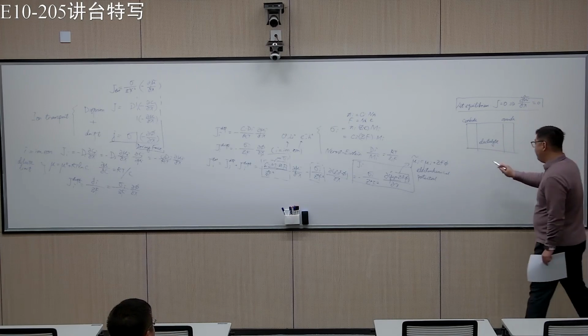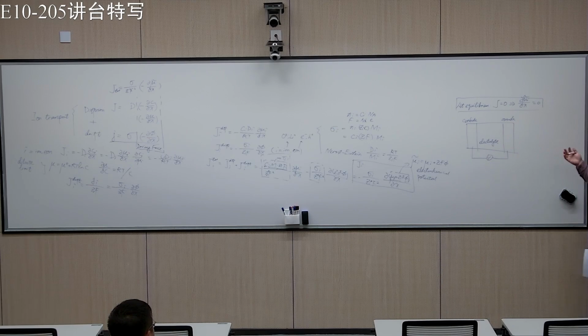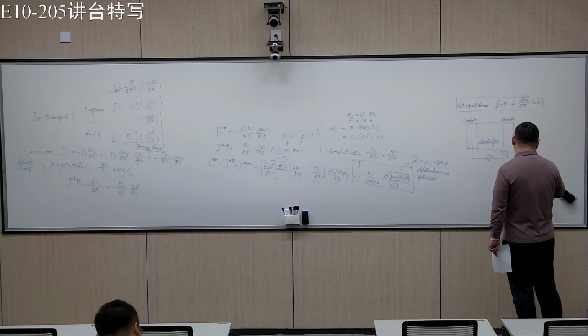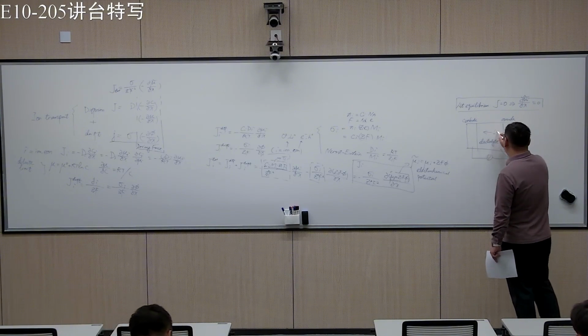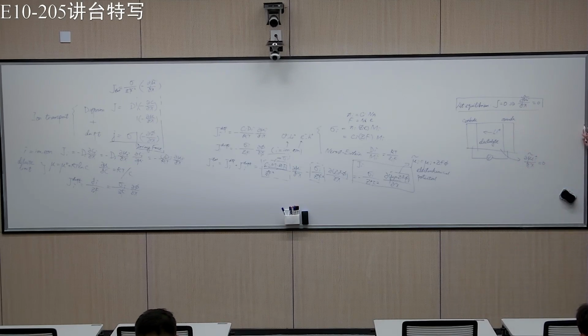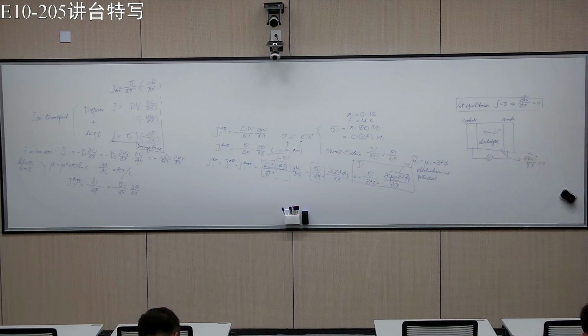Then if we measure the open circuit potential, which means that there's no net flow of charge, then in the electrolyte, for example if it's a lithium-ion battery, the electrochemical potential for lithium-ion should have no gradient, which means the electrochemical potential should be the same everywhere in the electrolyte.